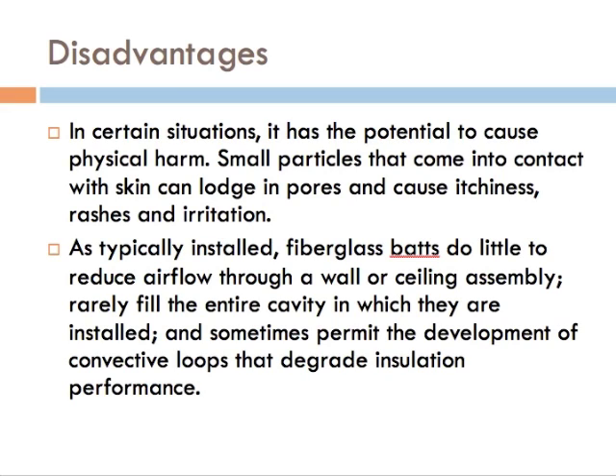However, the disadvantages is that it has potential to cause physical harm, because the small fiberglass particles can cause irritation to the skin when they lodge in the pores, and they can cause itchiness. Also, they do little to reduce airflow through the walls or ceilings, and they rarely fill the entire cavity where they're installed. They can sometimes permit the development of convective loops, which then degrade its performance over time.